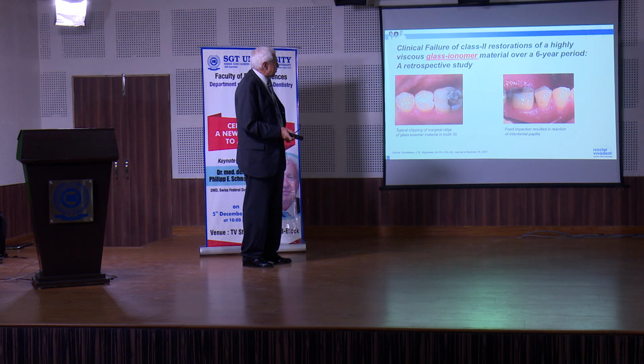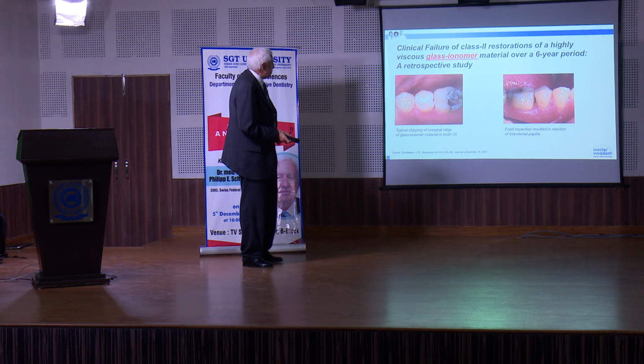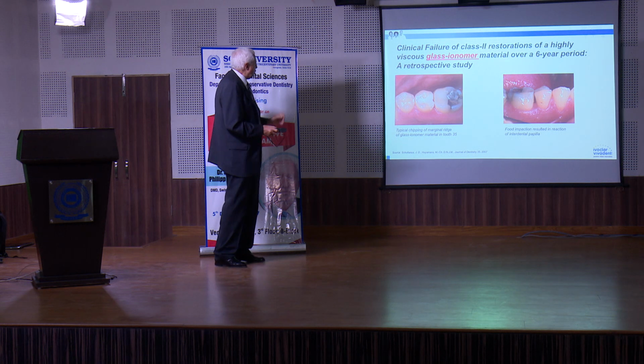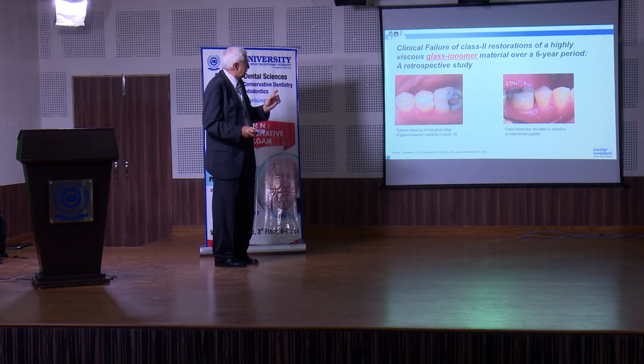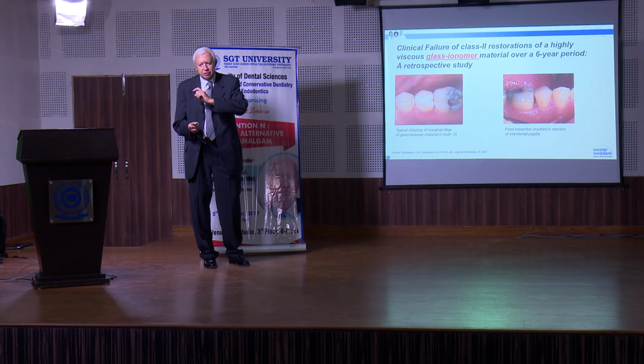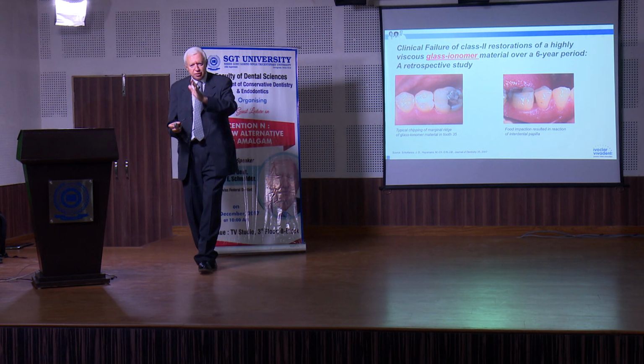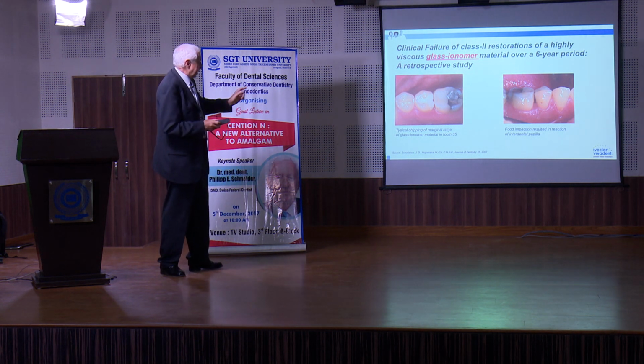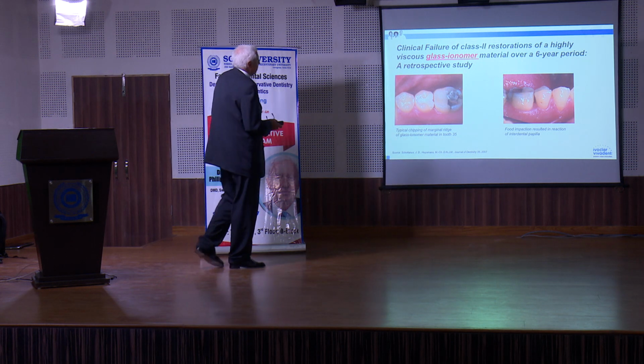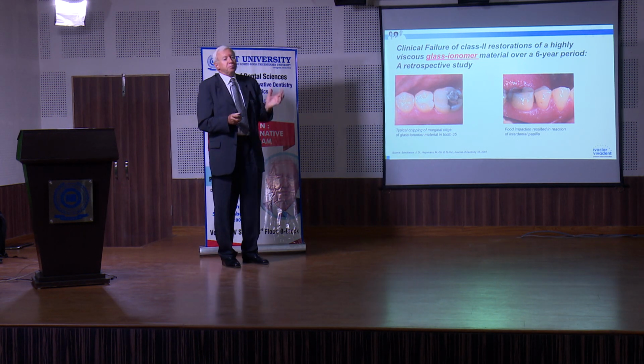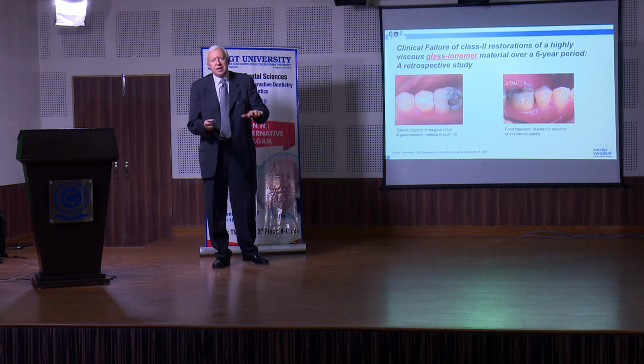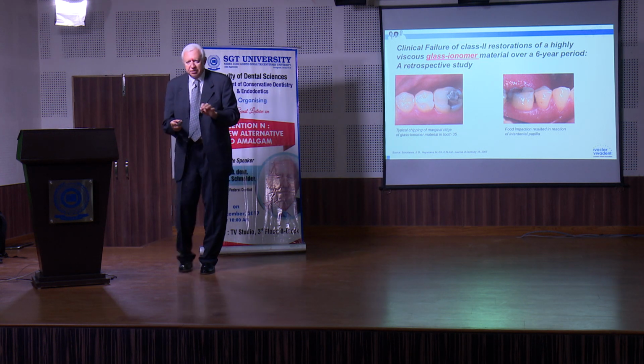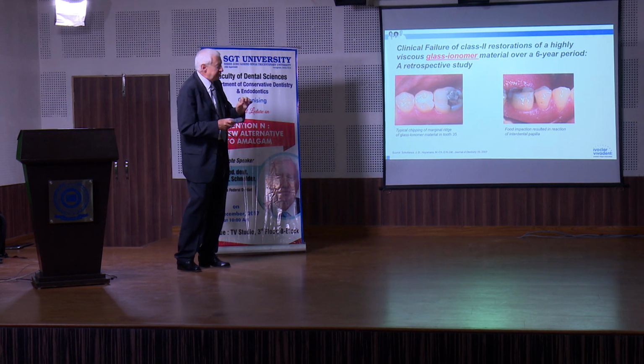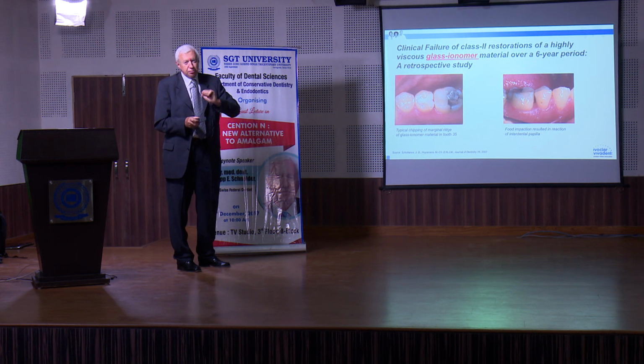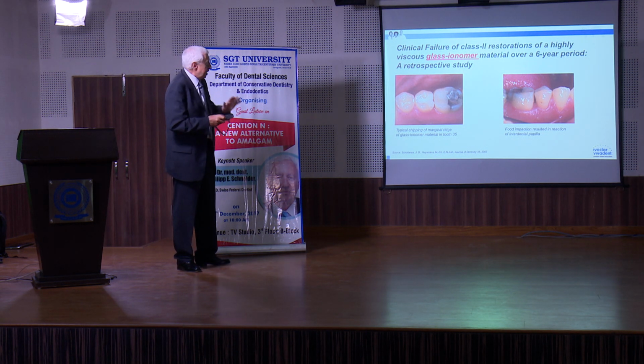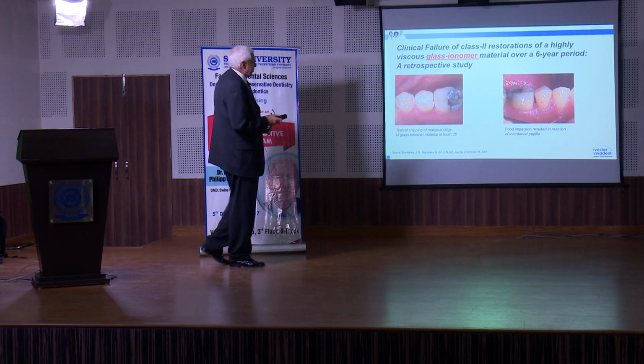Clinical failure of class 2 restorations over a 6-year period. And you see, always you have this typical chipping of the marginal ridge. It will not break at the isthmus. And this fracture will arrive about 6 until 8 months after placement. Okay, it depends on the occlusion, it depends on the cavity. But for the posterior region, it is really not suitable. For posteriors, premolars, molars, it's not suitable.